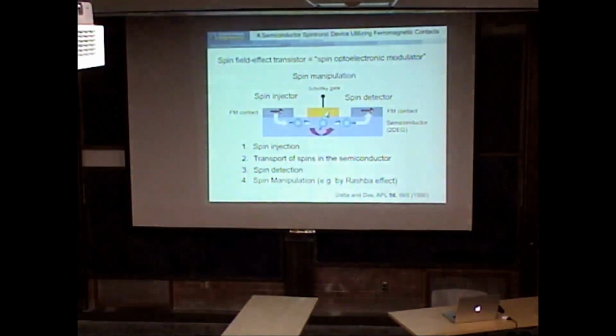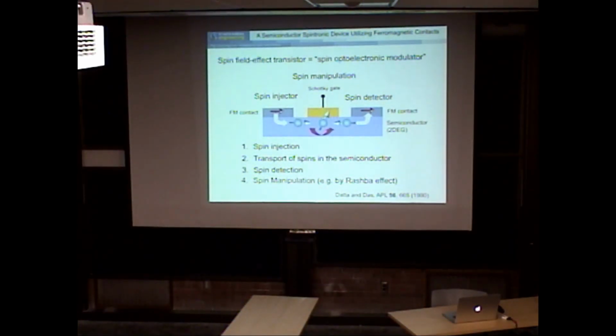Okay, so let's start off with this concept of a simple thing, the spin FET, which I would argue that no one's really made a spin FET yet that really works. But the concept is good because it gives us a reason why we're trying to do what we do. The idea here is, you really call it a spin optoelectronic modulator rather than spin FET, but the idea is you have a ferromagnetic contact, you can inject spins, transport them in a channel, and detect, using another ferromagnetic contact, the orientation of the spin, and in between, if you have a gate due to spin-orbit coupling, you can actually use a Rashba effect to manipulate those spins.